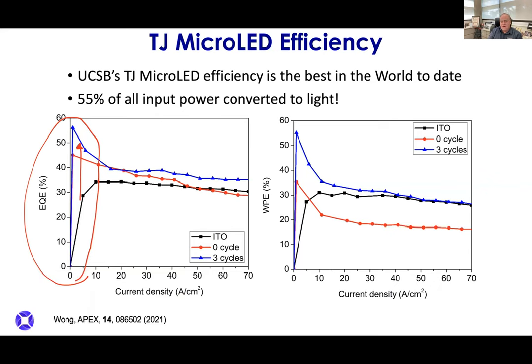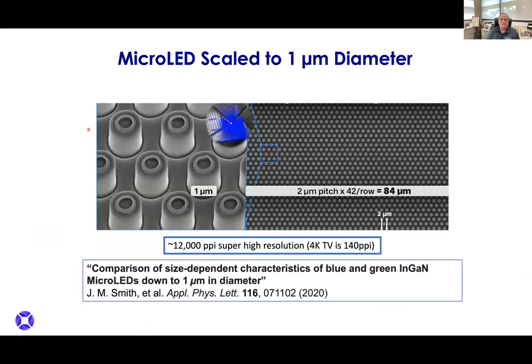So you can see how impactful semiconductor technology can be, because if you have a micro LED screen and it's only 20% energy efficient, a threefold increase will mean your Google glasses will last 3 times longer, which was the biggest problem, by the way, with display glasses: you have very little room to put a battery in these glasses. But if you have a very efficient display, we can now fit the battery in the frame, and you don't have to take off your glasses every hour and charge them.